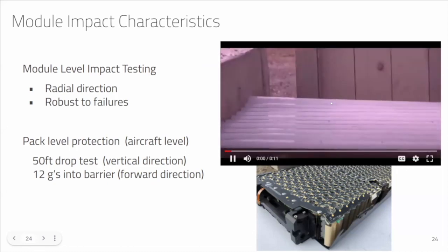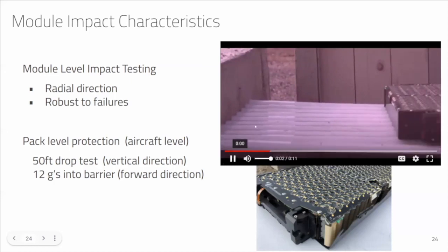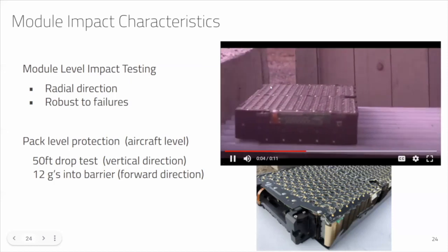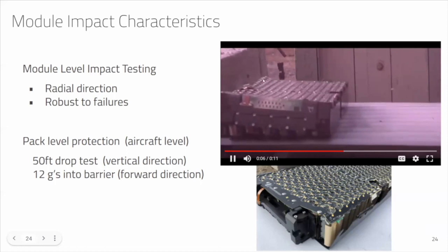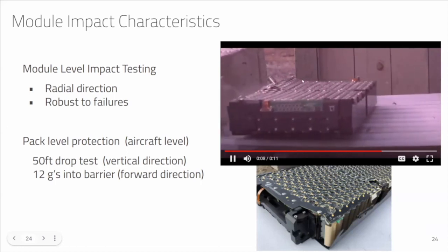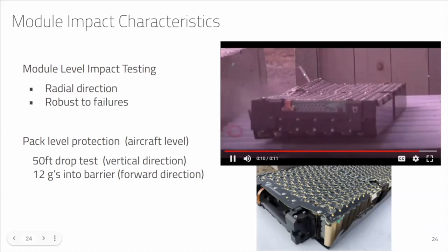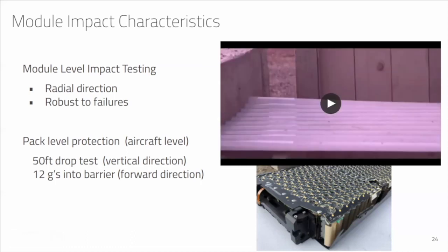There is a small amount of electrical arcing initially, due to the fact that the module does break some electrical connections at roughly the 50 volt potential. One cell is shown leaving this package. This still has to go through a lot of refinement, and we're changing the design, but it just shows you what sort of testing takes place after the cell is manufactured and brought to the integrator.